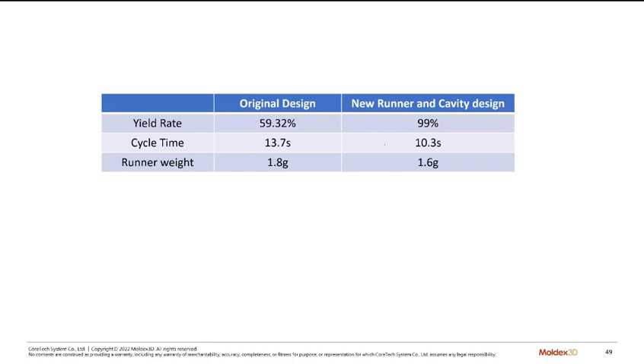And the cycle time reduced roughly 30%, and the runner weight reduced like 11%. Okay, so that's how they fixed the problem. First, they found the quality is unstable in each cavity, so they found out that the problem is caused by the unbalanced flow or the unbalanced runner design. They improved it to make it balanced, and then after each cavity has a similar quality, they can try to